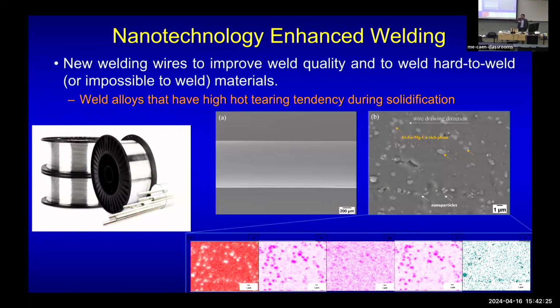Of course, I'll quickly move on to another certification application, right? You talk about welding. Naturally, we solved the casting problem. We know, okay, we do the high pressure die casting. We have a cooling rate of about 100 degrees C per second, and welding is exactly in that domain, about 100 degrees C per second, the arc welding. So we also commercialized, right? Put this wire, manufacture that, scale up production.